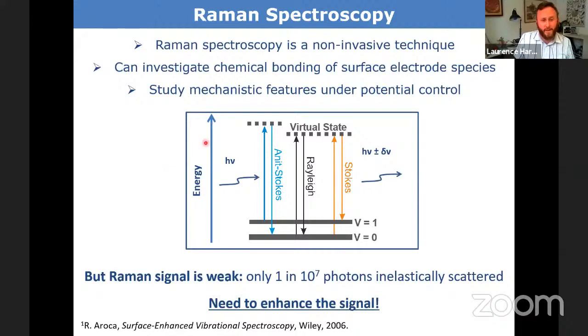So the Raman effect is that a coherent light source, such as a laser, can excite our sample, and it excites an electron to a virtual energy state. In most cases, predominantly, you have elastically scattered light where no energy is lost, so it returns back to its original state. But a small percentage, about 1 in 10 to the 7 photons, can be inelastically scattered. This inelastically scattered light gives us our Raman signal. The difference in the energies relates to the energies in the chemical bond.